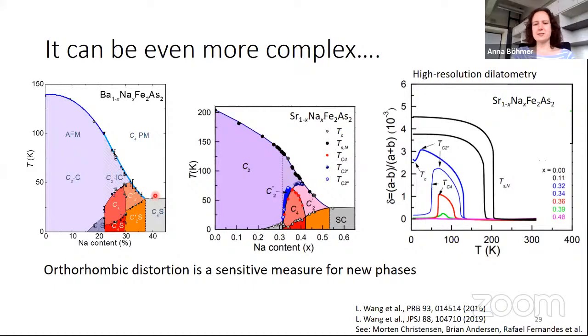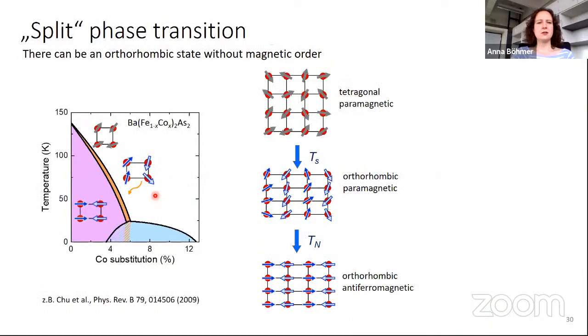There are even more phases discovered with this technique, which I will skip here, just in order to come back to one of the most interesting effects of this magnetism. We have discussed so far the transition from this square-like tetragonal magnetically disordered paramagnetic state to this stripe antiferromagnetic state. But it turns out, and this really was an experimental discovery at first, there can be an intermediate state.